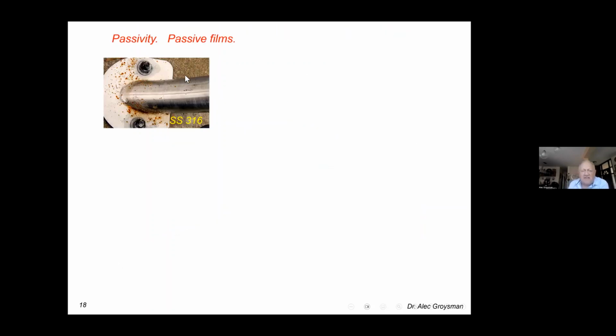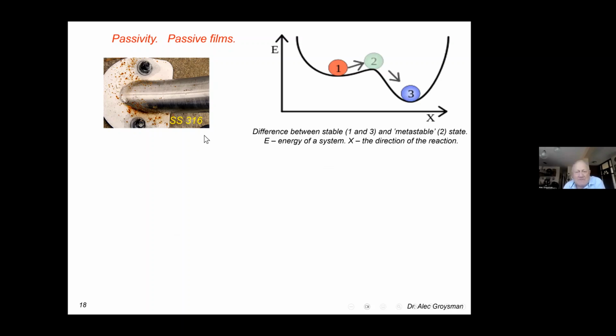What can we say about passive films or passivity that we observe on the stainless steel, for example, stainless steel 316, yes, and passivity in the metastable state. This is an energy system, the direction of the reaction. One and three are stable conditions, but usually we deal with metastable condition. Any change in concentration, temperature, flow rate may result in moving from metastable to corrosion. Thus, we see these corrosion points or spots on the passive films on stainless steel surface.